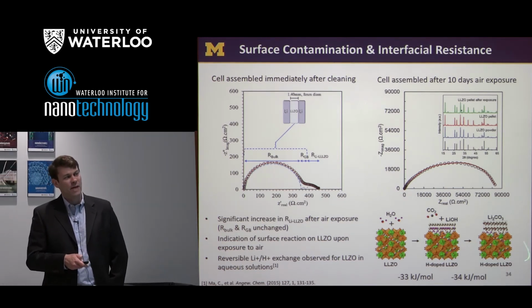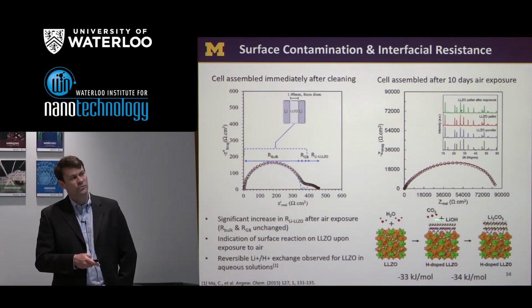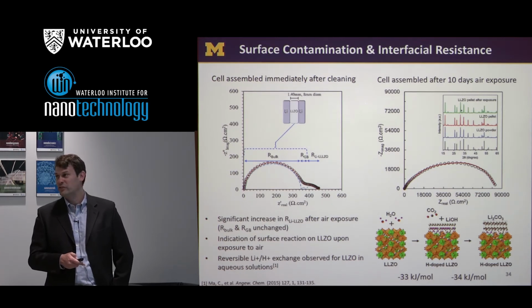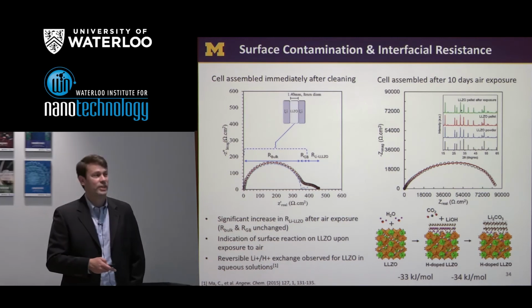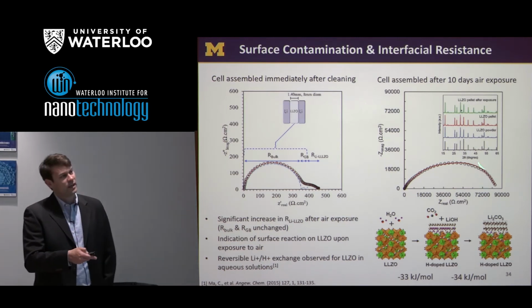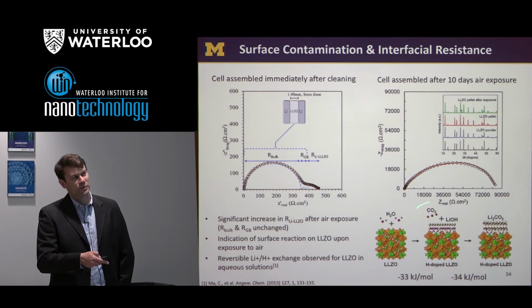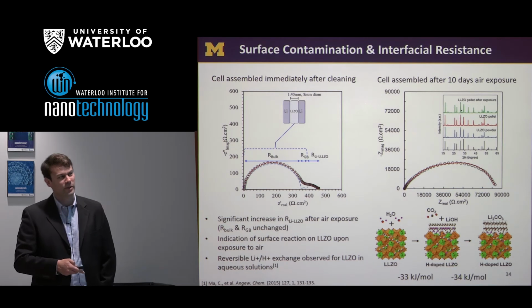And what we think is happening here, we've done some calculations of the thermodynamics of this process, is we think you start with LLZO, and when it sees some water vapor, it reacts exothermically to form lithium hydroxide, and also some of the hydrogen from the water goes into the LLZO. It displaces some of the lithium and protonates the LLZO. A second step is that if there's some CO2 in the atmosphere, that will then react with the hydroxide to form lithium carbonate. That's also an exothermic step.